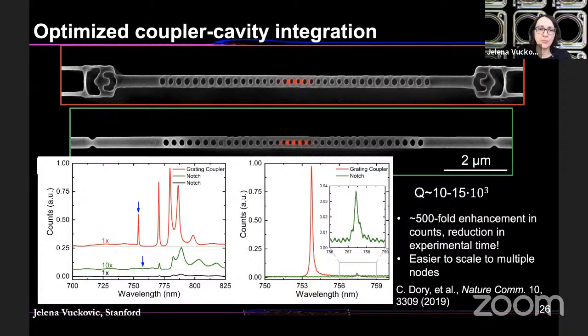And with the experiment, we can reduce experimental time. Instead of barely seeing a signal after you integrate for 10 seconds, after a single second, you see strong cavity signal. So you can kind of start thinking about scaling this up because you're not really limited by experimental times and signal to noise ratios. And of course, it's all about efficiencies. We're collecting many more photons in the system.